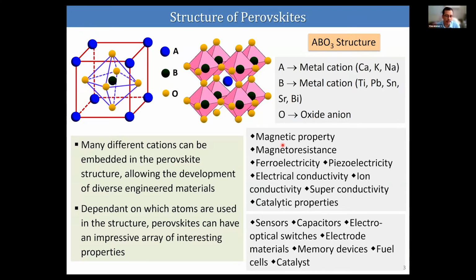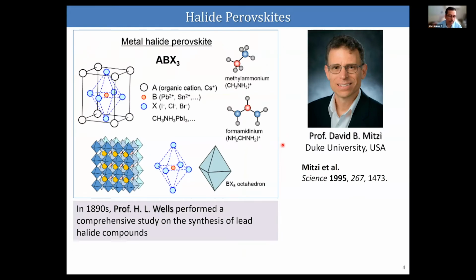This purely synthetic material was developed mostly by Professor H. L. Wells in the 1890s, and it has the same perovskite structure, but there is some difference. Here the oxide anions are replaced by halide anions like iodide, chloride, and bromide, and this can be represented as ABX3 instead of ABO3. Again, the X anions form an octahedral structure, and the B cation occupies the inside of the octahedron. Several of these octahedra join together to form a 3D structure, and the free space is occupied by an organic cation or cesium ion. So that's the difference.